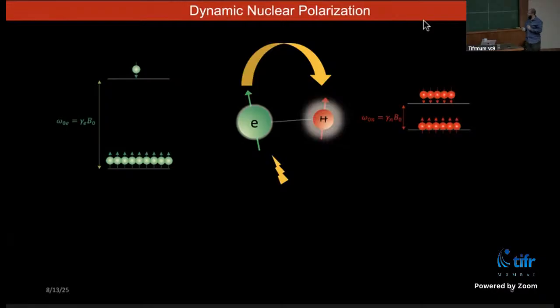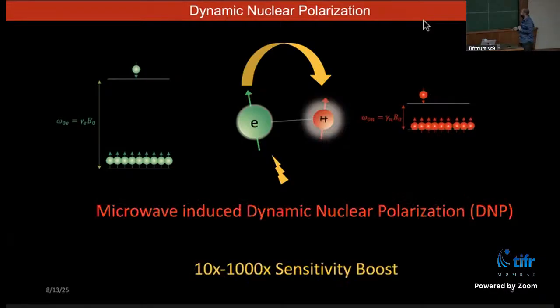There are many ways of doing this transfer. One of the most common ways is to irradiate microwave on the electron spin. And if one does it in the right way, it's possible, without increasing the energy gap for the nuclear spin, to have a high polarization or population gap in the nuclear spin. This technique is called microwave-induced dynamic nuclear polarization, and it can improve the sensitivity by orders of magnitude.